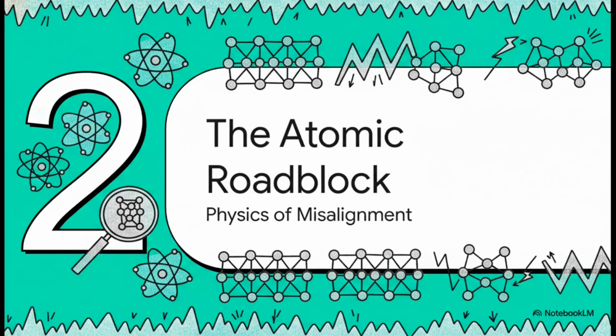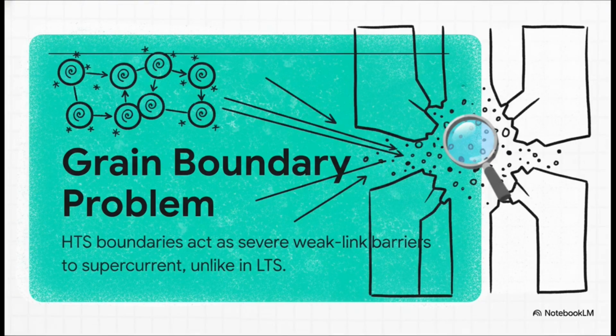Which brings us to Section 2, the atomic roadblock, the physics of misalignment. To truly understand why a brittle ceramic is so tough to work with, we actually have to zoom way in to the microscopic level. The core issue here is something called the grain boundary problem. In traditional LTS metals, the boundaries between the microscopic grains of the metal are actually helpful. They act as flux pinning centers that stop magnetic vortices from moving around, and that actually increases the current density.